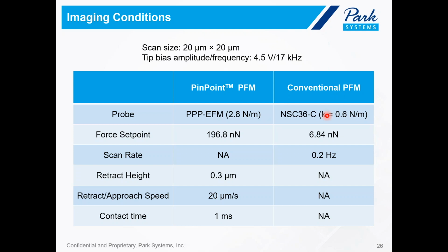The nominal radius is also 25 nanometers, and the scan rate was 0.2 hertz. I want to mention that for conventional PFM measurement, our initial attempt was to use the same cantilever, the PPP-EFM, which is what we use for the PinPoint PFM measurement. However, this probe was constantly scratching on the surface, and the imaging quality was not ideal.